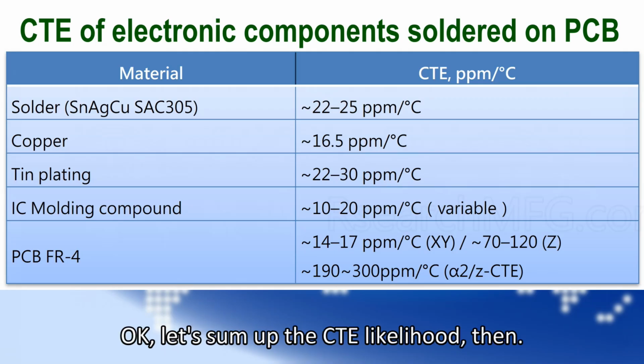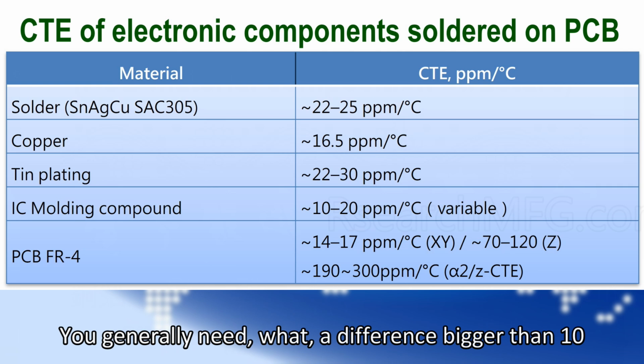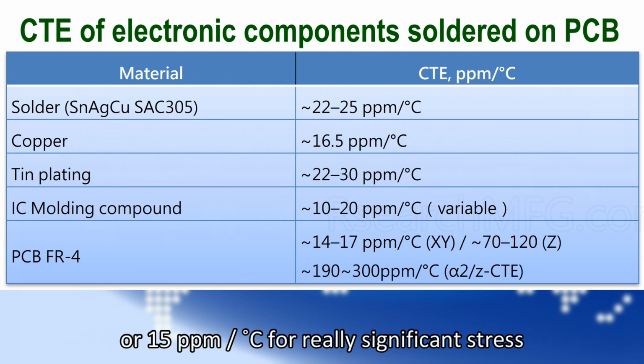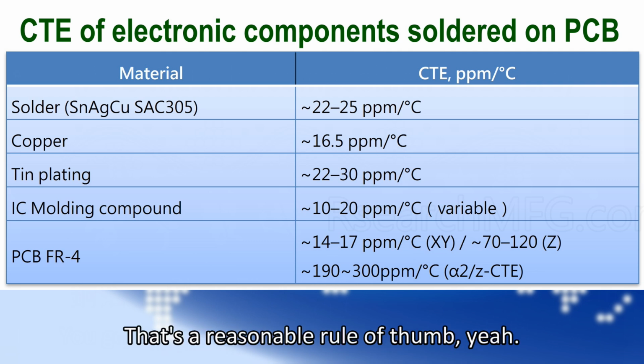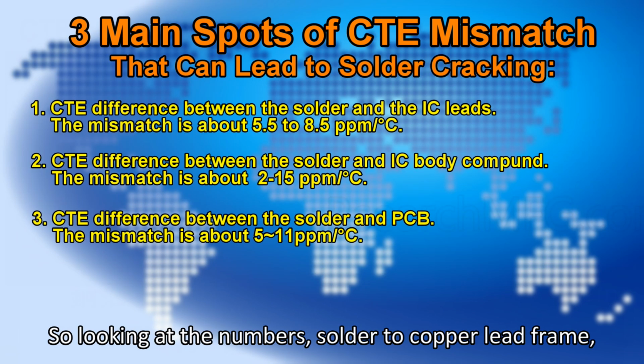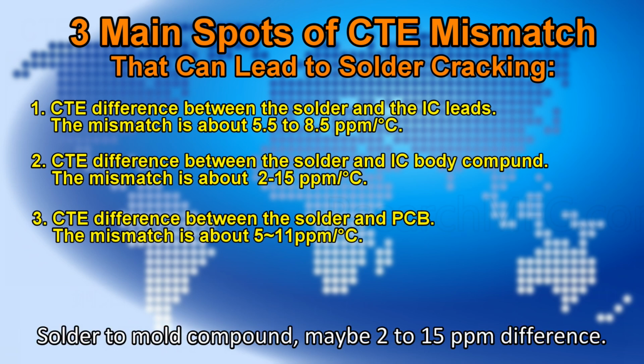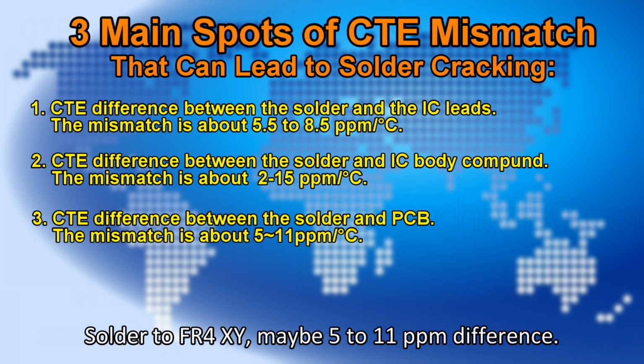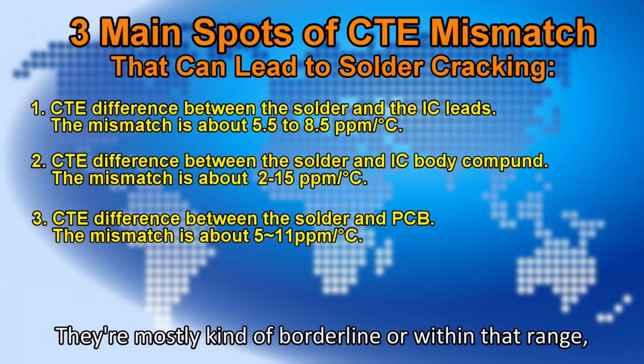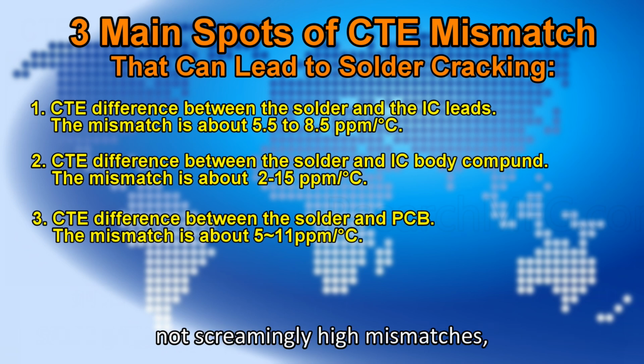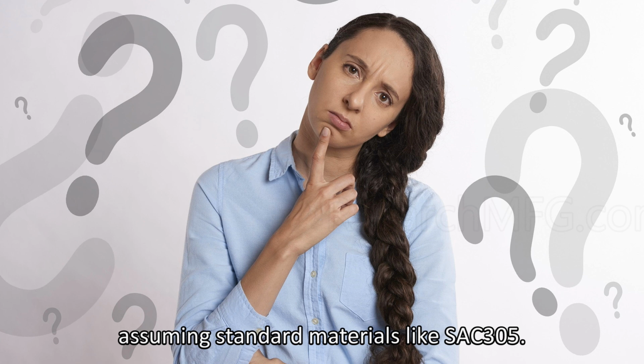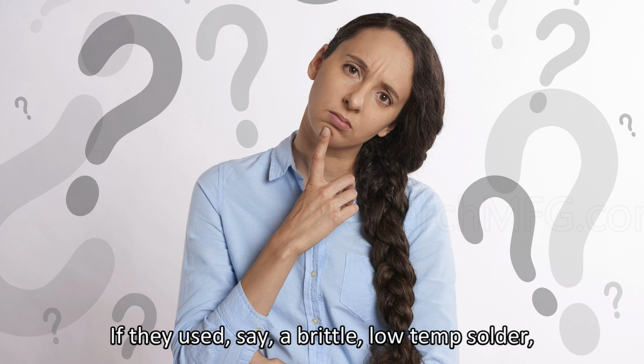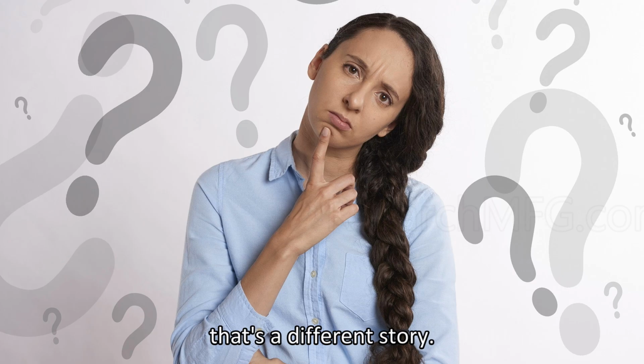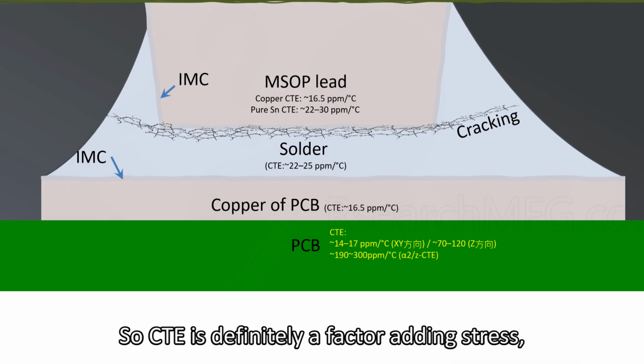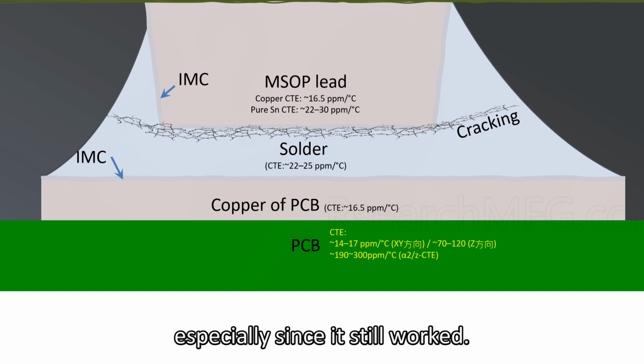Okay, let's sum up the CTE likelihood then. You generally need a difference bigger than 10 or 15 ppm per degree C for really significant stress and cracking from CTE alone? That's a reasonable rule of thumb, yeah. So looking at the numbers, solder to copper lead frame, maybe 6 to 9 ppm difference. Solder to mold compound, maybe 2 to 15 ppm difference. Solder to FR4 XY, maybe 5 to 11 ppm difference. They're mostly borderline or within that range. Not screamingly high mismatches, assuming standard materials like SAC305. If they used, say, a brittle low-temp solder, that's a different story. Right. So CTE is definitely a factor, adding stress, but maybe not the sole smoking gun here, especially since it still worked.